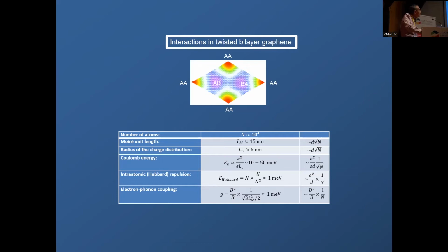And this effect is particularly important because, as mentioned already, the charges you induce when you apply a gate and you increase the number of carriers are not uniform within the unit cell. For instance, in regular graphene, you can apply a gate and you put more electrons into the bands, but the charge density associated to these extra electrons is uniform and is perfectly compensated by the potential created by the gate. Here, you create new charges because you are turning on a voltage, a gate. But in addition to a constant potential, you have a periodic potential within the unit cell, which is large and which is unavoidable. I mean, it's related to the particular topology of the wave functions of these bands.